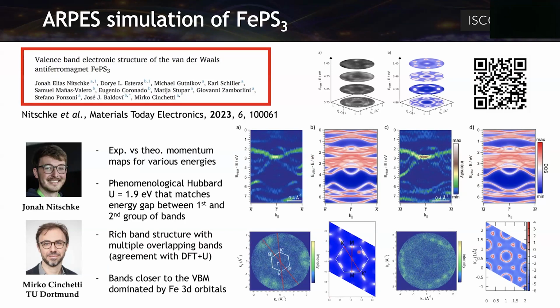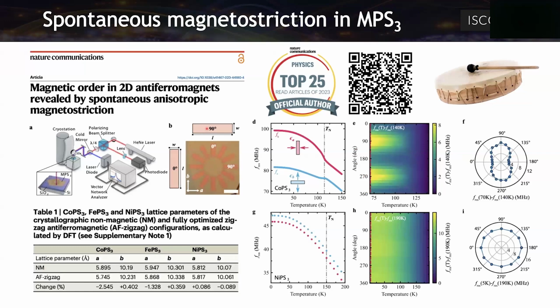And we were also getting, for the different cuts of energy, the rich band structure, and we could determine which are the orbitals that are playing the main role here, that are the iron 3d orbitals. This was also published last year in Materials Today Electronics. So another work in collaboration with experimentalists, in this case, also the samples from Eugenio and experiments in Delft by the group of Van der Zant. And in this case, they were working with membranes of this material, with iron PS3, cobalt PS3, and nickel PS3.